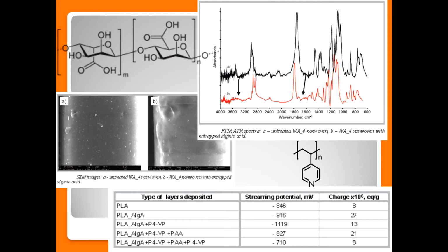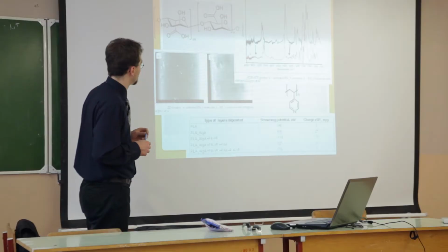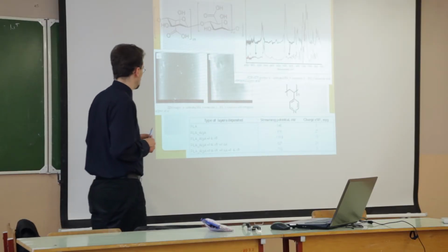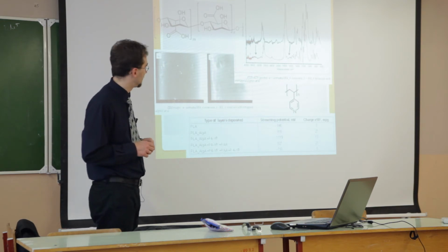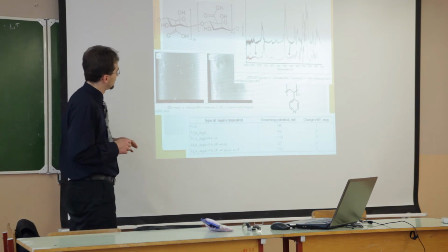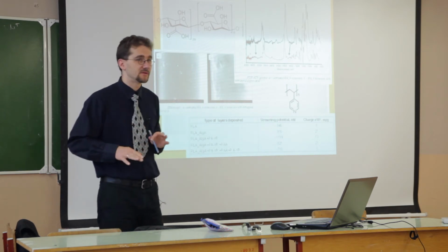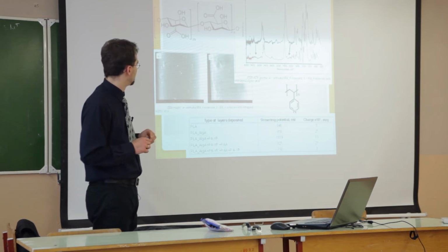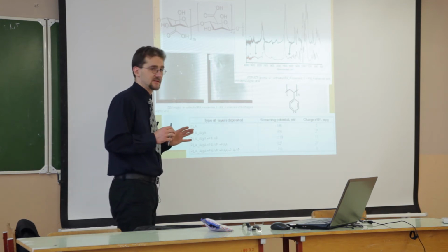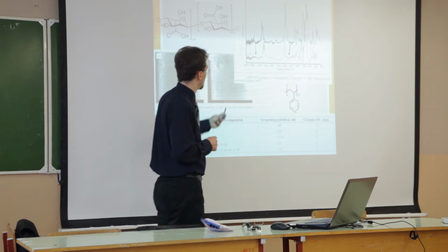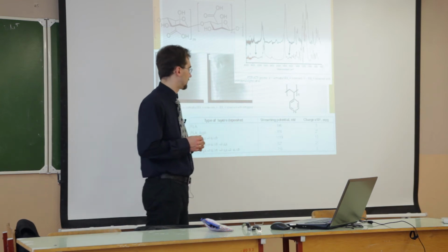Also, alginic acid was entrapped on the surface, and we examined the surface using SEM microscopy. The surface before and after modification is slightly different, but not strongly so. At the beginning it is very regular; after modification we can see some irregularities. We again used FTIR ATR spectroscopy to control the structure of the surface.